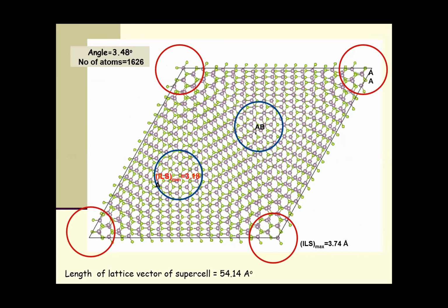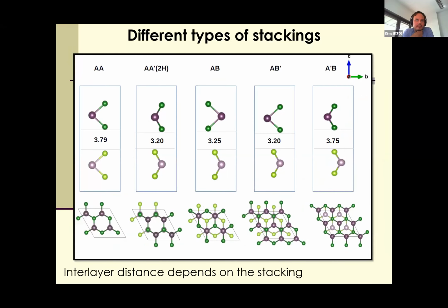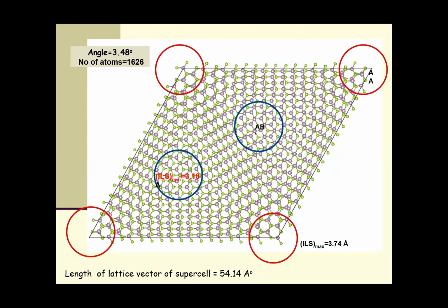That's the main idea: when you go to the large angles, with the strain, you're never going to see only one particular type of these high symmetry stackings that I was talking about. It's only at these small angles, close to 0 degrees and close to 60 degrees, that you'd see it, because otherwise the moment you move away, every next layer would be moving further away. And so you never have a large enough patch which is a particular high symmetry stacking.